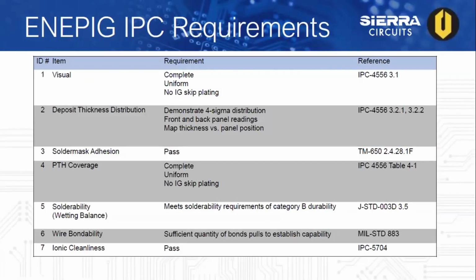As we saw with ENIG, we put a table together for the IPC requirements. After plating ENEPIG, we want to make sure we have complete ENEPIG coverage on the substrate, and also on the plated through holes themselves. Thickness distribution should also meet the IPC criteria for nickel, palladium, and gold, from front and back and center and edges of the panels. This is important just to make sure you don't have any wonky different results throughout the panels.